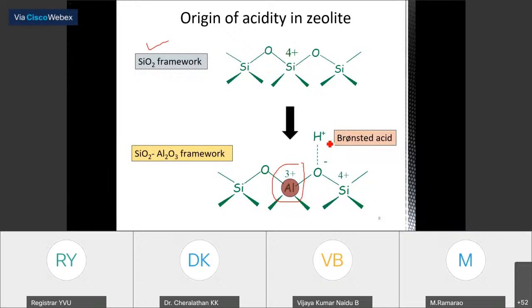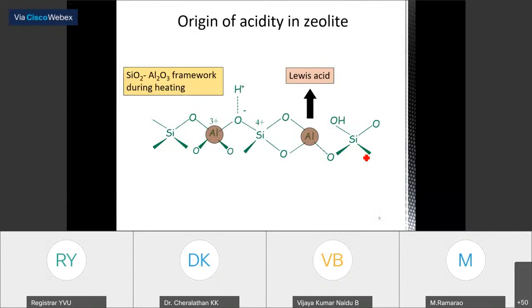And not only this proton, you can sometimes have sodium, potassium, even cesium, replacing this kind of cation. In that case, accordingly, the nature of this solid can be varied. If you have cesium, then you will have more basic sites in the zeolite. Completely, the property of the zeolite changes from acid to basic. That is possible. So not only Brønsted acid sites, Lewis sites can also be generated in the zeolites.